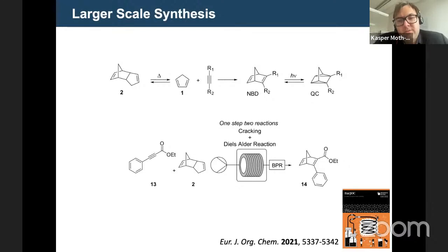What we are also working on is trying to develop scalable and green chemistry routes for how to produce our molecules. And here's one example where we try to simplify and scale at the same time. In a traditional way of making the molecules, we start with a cyclopentadiene dimer that you can crack through a retro-Diels-Alder to form cyclopentadiene. And then you do the forward Diels-Alder with your dienophile and make the molecule that you can later photoswitch. So here we use an automated flow chemistry system where we heat everything inside a small tubing, and then we crack and react at the same time. So we do 2 chemical reactions together and form the molecule without having to do any workups or any complicated things. It's only happening in a few minutes.